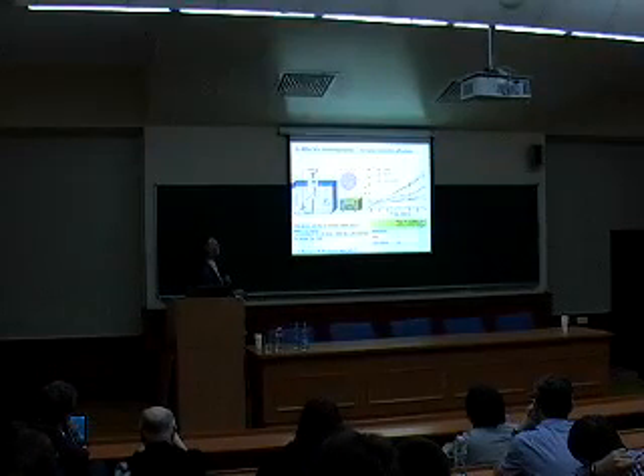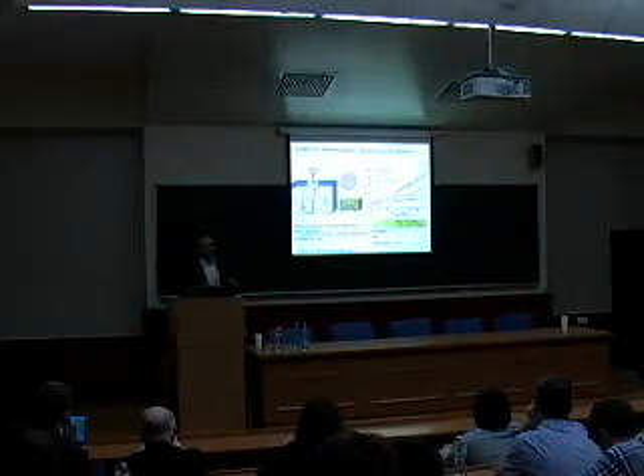We observed suppression of cancer cell growth in mice. And here you see the relative volume of tumor for the reference group, the black points; the group with introduced nanoparticles, green, without any effect; and the red group, which is the combined action of nanoparticles and ultrasound. You see the strong suppression, more than 2 to 5 times suppression of cancer growth. Therefore, these nanoparticles can be a very efficient therapeutic agent for what is called sonodynamic therapy.